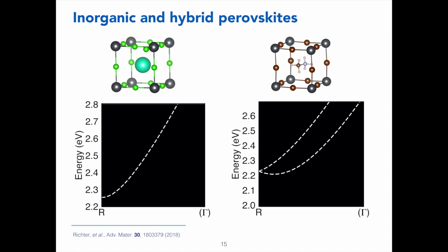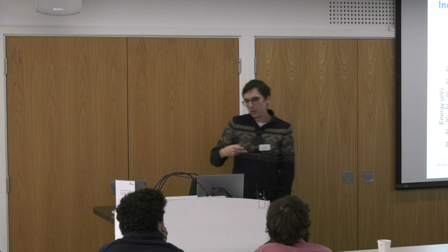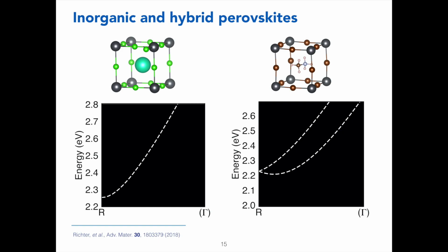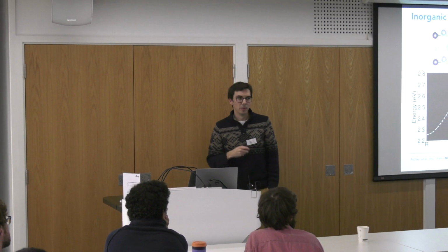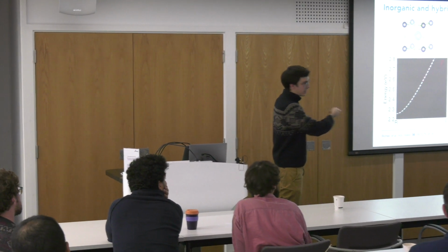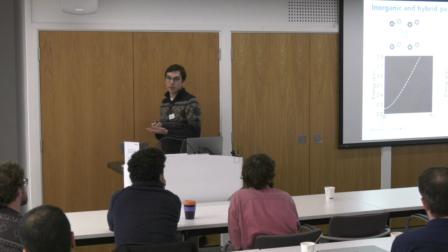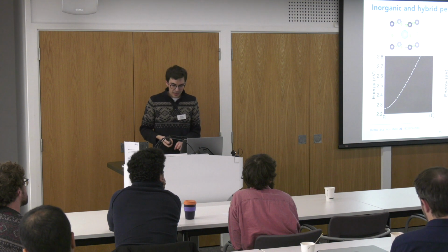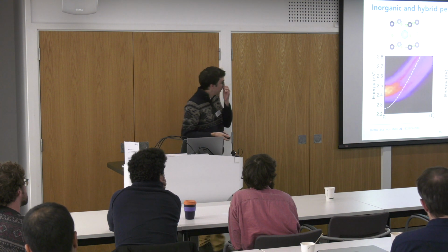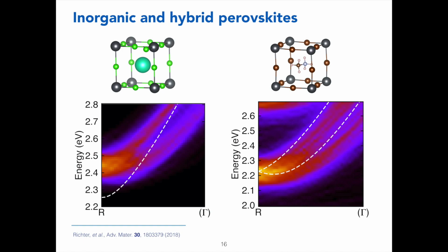I raise this point because this splitting has been quoted many times in the literature as being one of the reasons why these materials behave the way they do. For example, suggesting that it helps suppress the recombination rate because it creates a slightly indirect band gap due to this Rashba splitting. Now, Felix Deschler's group were doing experiments, and they were finding no difference whatsoever between the behavior of this inorganic material and this hybrid material, which seems to be contradictory with these band structures that I have calculated here without any dynamic disorder. So what we tried to do next was to include the effects of dynamic disorder, and when we do that, that's what we find. So suddenly, the two materials look very, very similar.